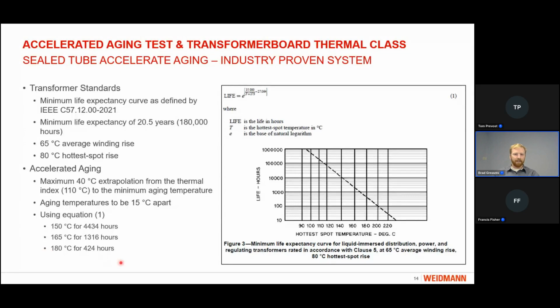So at 150 degrees, we have an aging period of 4,434 hours. At 165, it's 1,316, and 180 being 424 hours. And again, these are all points on this minimum life expectancy curve, which are equivalent to the 110 degree C thermal index and the 180,000 hours.